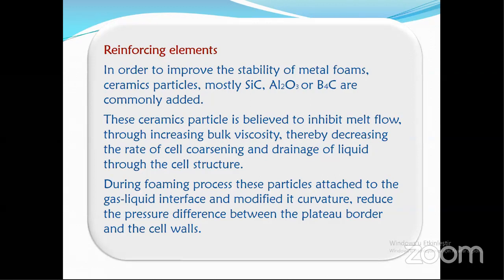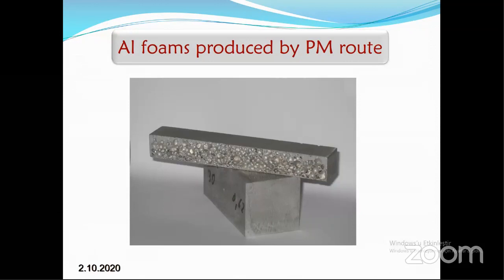Sometimes we are using reinforcing elements. In order to improve the stability of metallic foams, ceramic particles, mostly silicon carbide, alumina, or boron carbide, are commonly added. These ceramic particles are believed to inhibit melt flow by increasing the bulk viscosity, thereby decreasing the rate of cell coarsening and drainage of liquid throughout the cell structure. During the foaming process, these particles attach to the gas-liquid interface and modify its curvature, reducing the pressure difference between the plateau border and the cell wall.